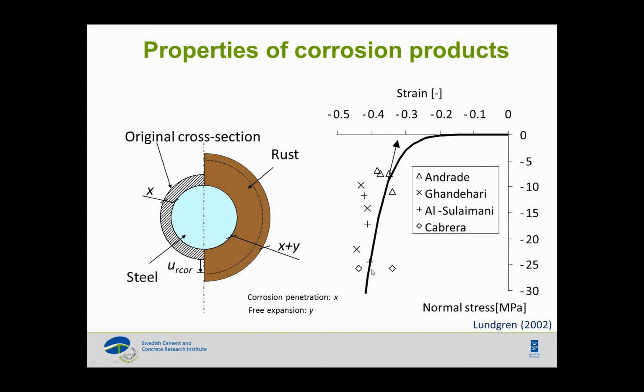And what we have come to back in 2002 was that actually rust is a granular material, meaning that when you put pressure on it in the beginning, it takes the pressure, it has a lot of deformation, but later on the stress, with a little bit higher strain, the stress really raises up, which means that we are dealing with a granular material. So that was the first time ever mechanical properties of rust has been estimated for this type of analysis. But later on in 2005 and also in 2013 there have been experimentations and also simulations approving or verifying the granular behavior of rust.